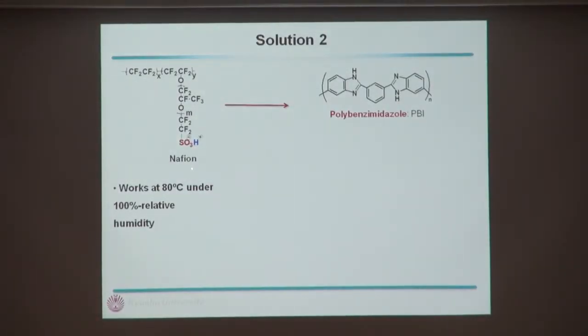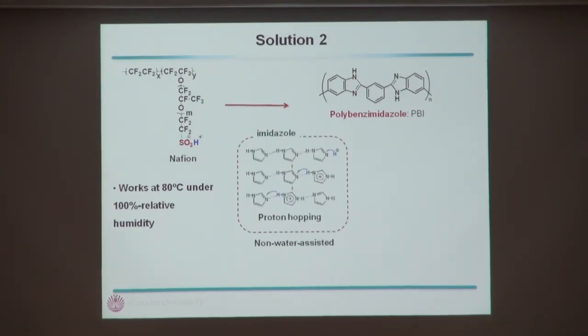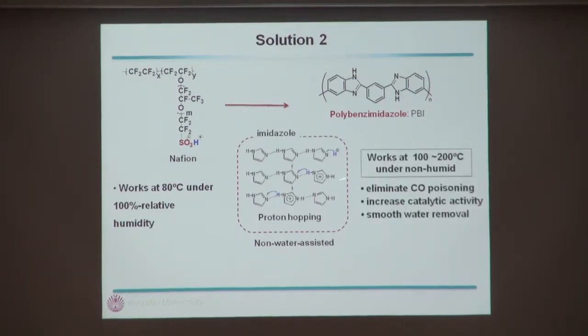And as an electrolyte membrane, we don't use Nafion. Nafion is a widely used electrolyte material, proton conducting material, but the cost is expensive, and their working temperature is usually 80 centigrade and 100% relative humidity. That may be not good. And our idea is to use polybenzimidazole, because when we use this polymer material, the working temperature range is very wide, so we can use the material over 100 centigrade and non-humid. That is a great advantage for fuel cell material.